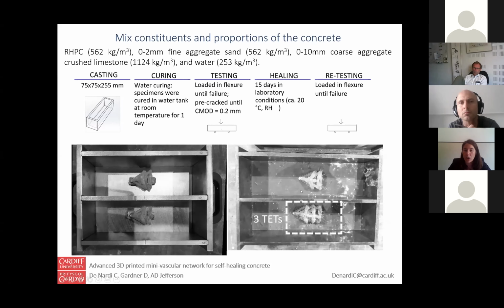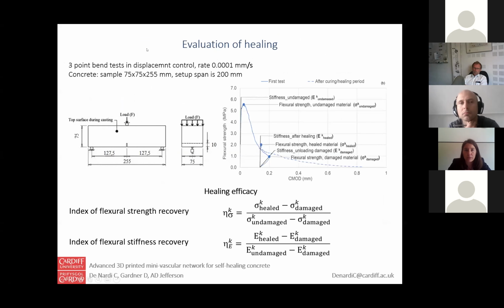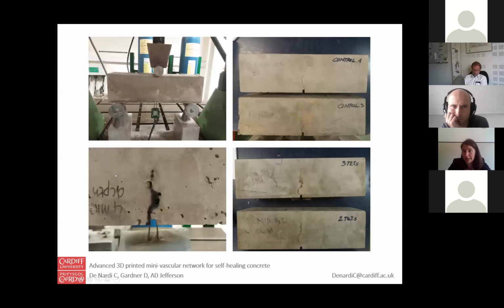As you can see here on the right, we placed in the center of the prisms 3 TETs or 2 TETs, and the samples were placed on 10 millimeter concrete spacers. Then we evaluated the healing efficacy by means of the 3-point bend test. So basically, we compare the flexural strength after the healing with the flexural strength in undamaged condition, in relation to the level of the damage. And we did the same for the flexural stiffness.